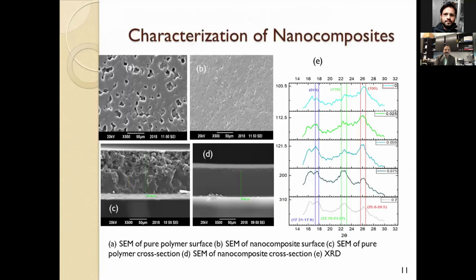The characterization of nanocomposites is the second part. Before the characterization of nanocomposites could begin, however, we had to look at the pure polymer membranes. We can see that there are distinct and very visible pores on the surface of polyethylene terephthalate membranes, which are blocked by only a small addition of nanofiller, such as boron nitride.